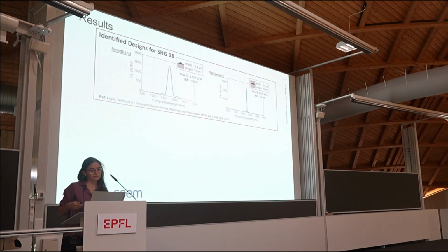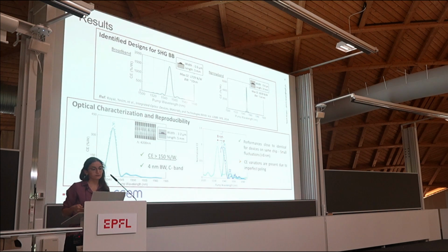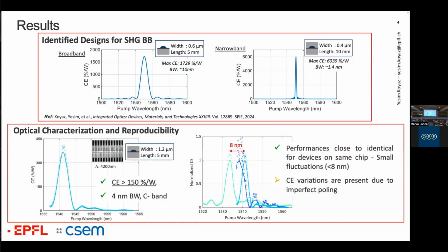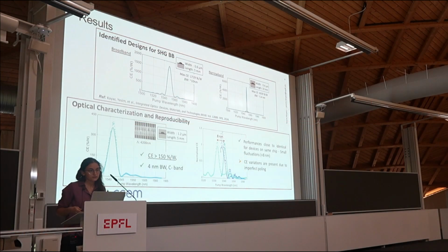Here are some of the results. We identified the designs for broadband operation or for narrowband operation with a range from 10 nanometer to 1.4 nanometer. We experimentally verified our designs of 4 nanometer bandwidth and achieved a conversion efficiency of 150% per watt. It is modest for lithium niobate, but still quite high considering other platforms. We also experimentally repeated our tolerance analysis and saw that the performance in terms of the SH peak position is close within the chip that we are investigating. We also see variations due to imperfect poling and between the wafers.